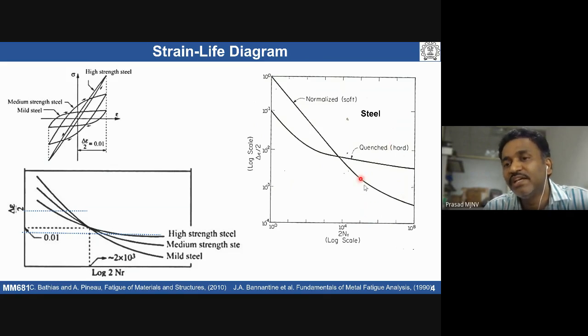In the high cycle fatigue regime, in order to initiate a crack in high strength materials, because there is a stress concentration, we need to apply some minimum stress. Then only we see crack initiation. So high stress is required to initiate cracks in hard material, martensitic steels, as compared to normalized steel. Any doubts here?